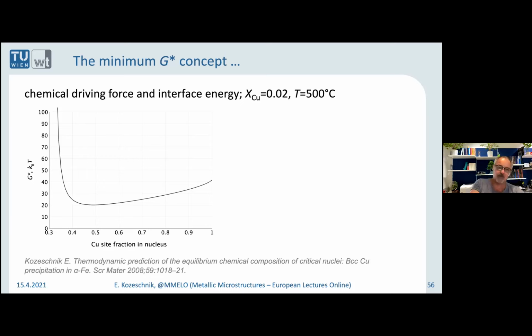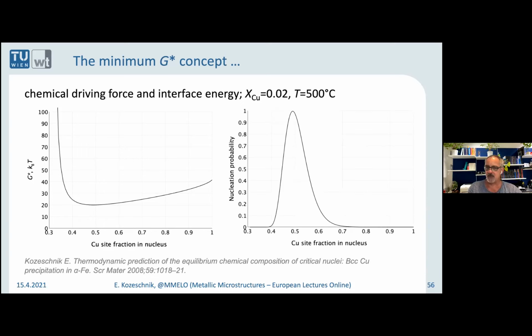Okay, now you can say, yeah, but this is not very much. Yeah, so it's 20 kBT and the other one is 40. It doesn't make a difference. It does make a difference. Once you put that into the exponent, you can see that the probability of nucleation becomes very sharp around this 0.5. So the theoretical prediction was that the copper nucleus will contain roughly half iron.